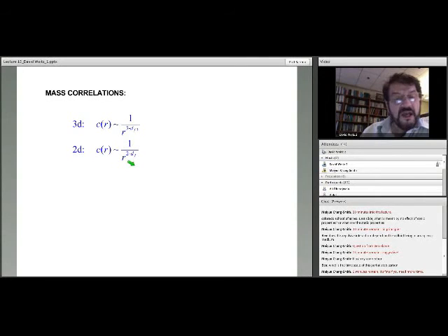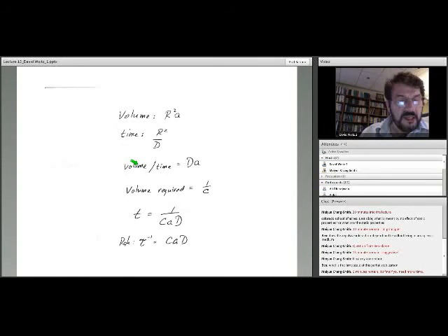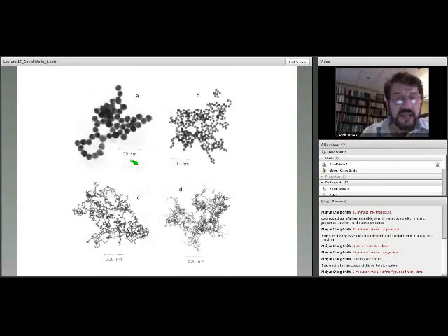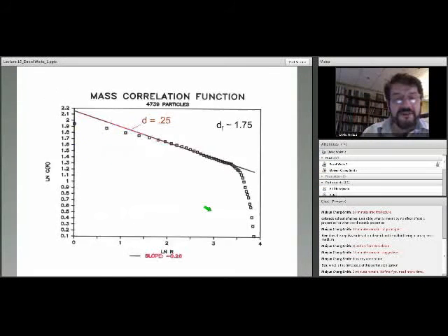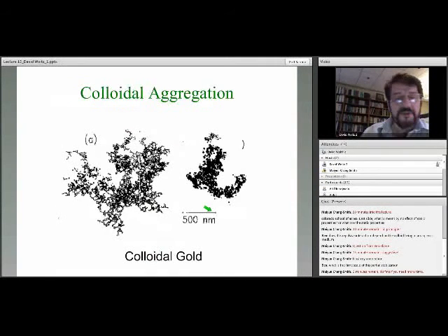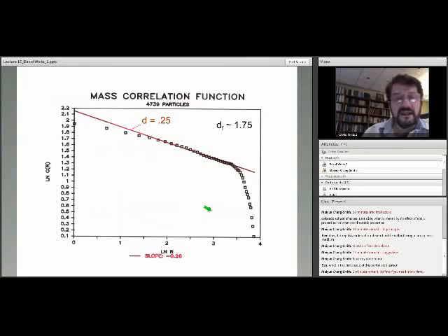And so if I go back and look, let me show you this image here. If I look at this image and I calculate the particle-particle correlation function between all pairs of particles, I end up with data that looks like this. And you can see that, plotting it on a log-log scale, there is a power-law decrease in the correlation function.